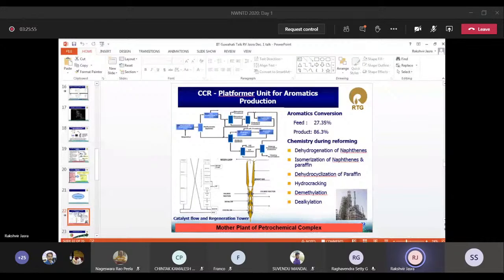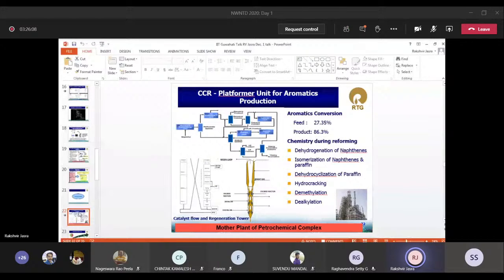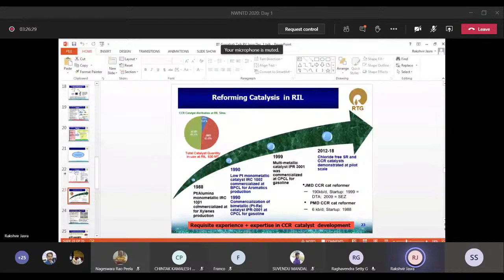Some of these reactions are desired, some are not desired. Now you have to develop a catalyst which can do all these activities, and it should do more of those activities which you want it to do and less of those which you don't want it to do. Like we don't want it to do hydrocracking, demethylation or coke formation. We want it to do more of dehydrogenation, dehydrocyclization or isomerization. Now this catalyst which is normally used is platinum and tin on alumina. It means you have to put platinum and tin on an alumina support.